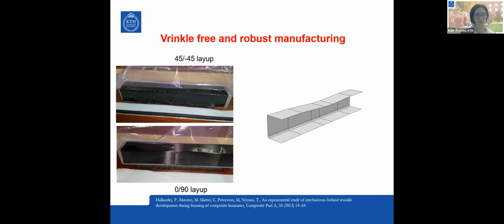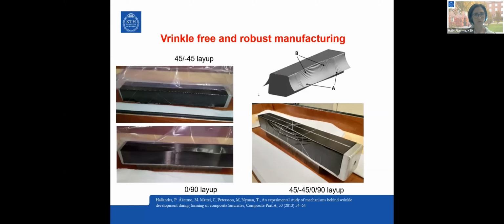We also saw that if you have a 0 layup or 0-90 layup, you got really nice geometry afterwards. However, if you stack those two layers together, plus 45 minus 45, 0-90, the forming comes out with severe wrinkles. So these wrinkles do not depend on having too much material in this area, not primarily at least, since this distance is longer than that distance. The wrinkles come from the different movement of the different layers. We have defined different kinds of wrinkles. So we have the micro wrinkles that depend on how these interact, the micro level wrinkles.